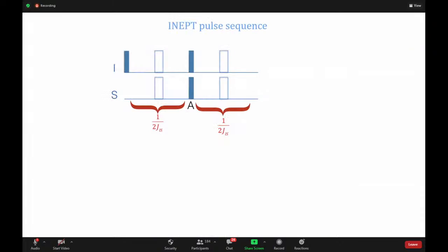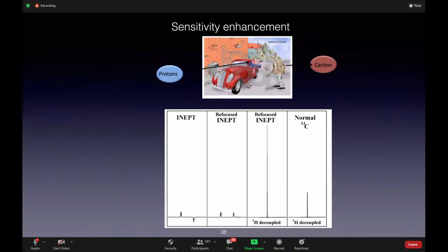Now carbon-13, I told you, is highly insensitive. As pulse programmers, we can actually increase the polarization or magnetization on the carbon using the INEPT sequence, insensitive nuclei enhanced by polarization transfer. That is like taking the magnetization of the rich guy, proton, and giving it to the poor guy, carbon-13. You can use a series of pulses interspersed with delays to focus the magnetization to flow in one direction. And that is possible.